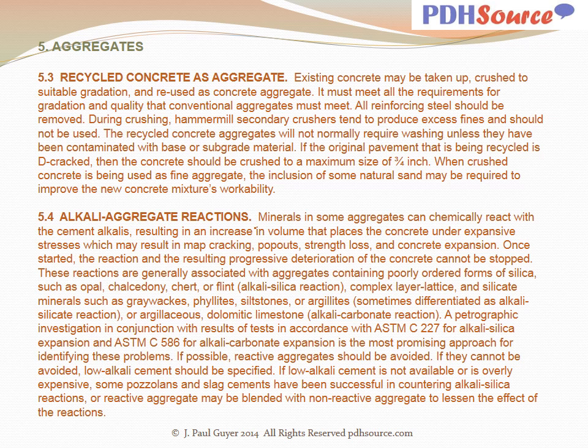During crushing, hammer mill secondary crushers tend to produce excess fines and should not be used. The recycled concrete aggregates will not normally require washing unless they have been contaminated with base or subgrade material. If the original pavement that is being recycled is D-cracked, then the concrete should be crushed to a maximum size of 3/4 inch. When crushed concrete is being used as fine aggregate, the inclusion of some natural sand may be required to improve the concrete mixture's workability.